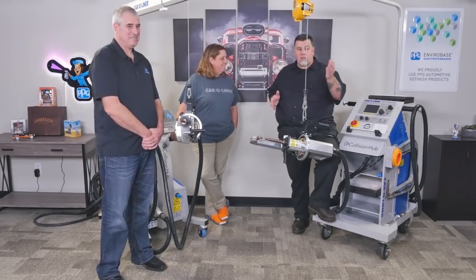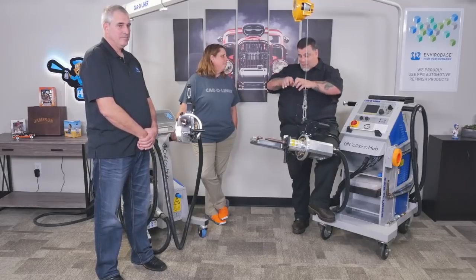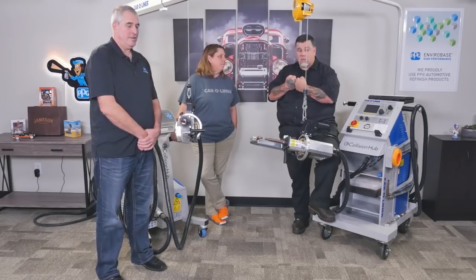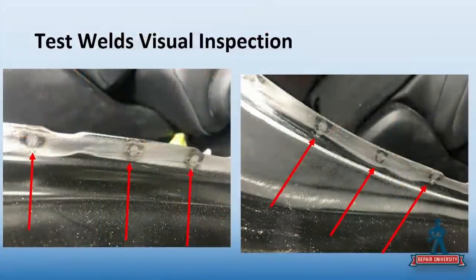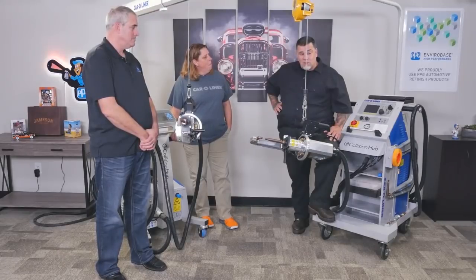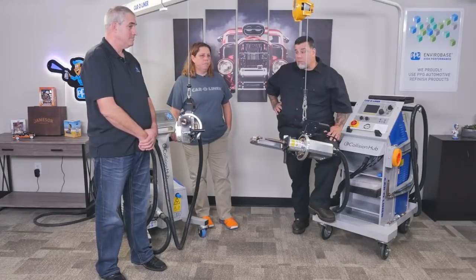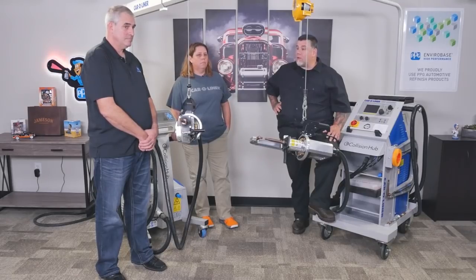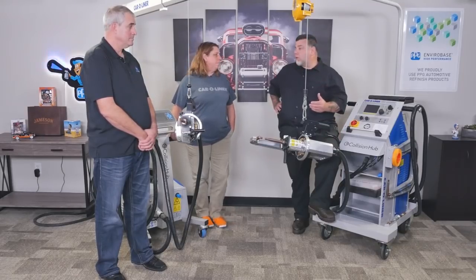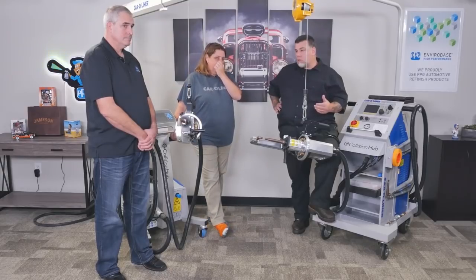But if I did a test on these, I could probably rip them apart by bare hand by just peeling them back against each other, a peel test. It looks like that lower picture on the left, with the weld to the right. It looks like there's a crack on the inside too. Yeah, that's going to cause some issues. And once again, this is funny. This was in a paint booth, ready to be primed and painted, and I still see weld soot. So not only was the machine not welding right, not only did the tech not really know what he was doing, but whoever prepped this didn't even do a good job.